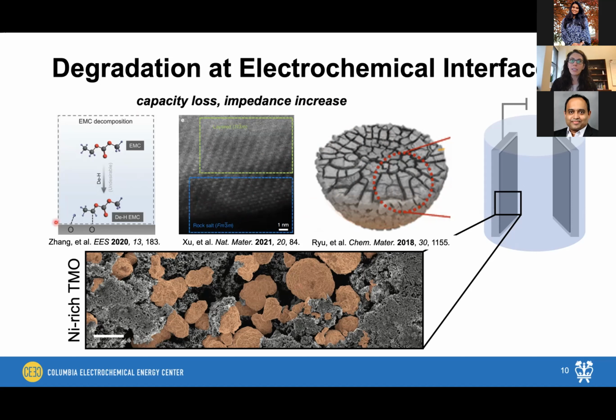But things like the electrolyte decomposition are a bit harder to study because we have the formation of these very fluffy organic decomposition products that are depositing all over the surface of this very heterogeneous composite. So these aren't going to diffract very well in things like an electron microscope. So they're much more difficult to understand the structure and the composition of.